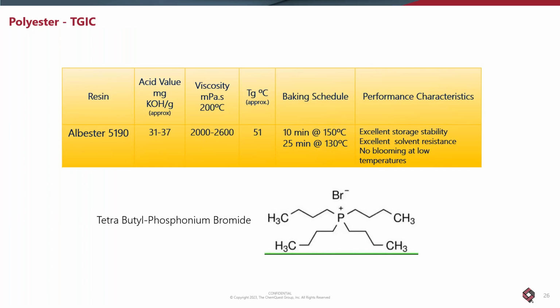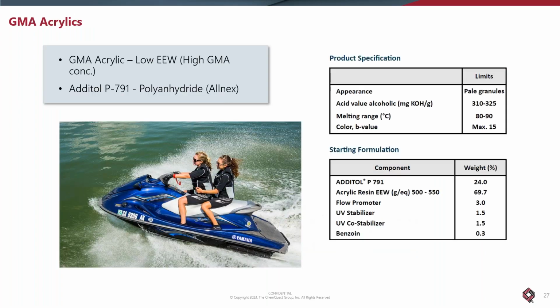TGIC, again, it's a kind of a combination of getting the right rheological behavior at these lower temperatures. So basically you need a decent melt point and also a relatively low melt viscosity at this, kind of 130 to 150 degrees C range. And then kind of utilize some clever catalysis. This TBAP type catalysis system seems to work quite well. It's got a little bit of latency, and it's pretty quick at this lower sub 150 temperature range.